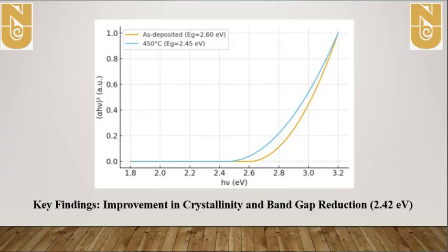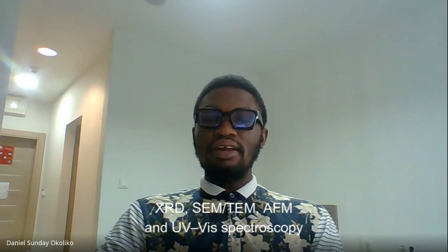Afterward, the films were exposed to an argon ion beam at high currents and controlled energy. This irradiation introduced defects and lattice strain, which I hypothesized would fine-tune the film's electronic structure. Now, to characterize these changes, I used advanced techniques including X-ray diffraction (XRD), scanning electron microscopy (SEM), as well as atomic force microscopy. Now, the result and the interpretation.